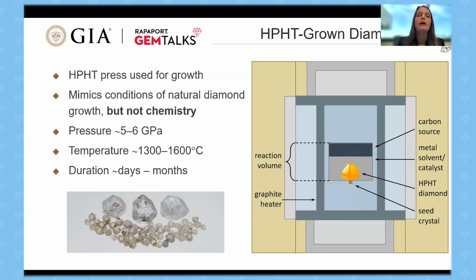The pressures that they apply are fixed at 5 to 6 gigapascals, temperatures up to about 1600 degrees Celsius, and depending on the quality and quantity of diamonds that you're trying to produce, it can be running between days to months.